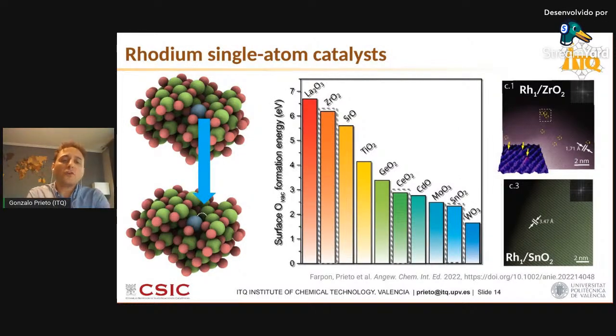At the beginning of this project, we set out to investigate one of these degrees of design for single atom catalysts, which was in particular our capacity to generate oxygen vacancies in the vicinity of our single metal atoms. Because already in other technologies, such as sensing, for instance, for light olefins, sensors rely on this interaction between olefins and oxygen vacancies, those type of surface defects. And that was the rationale we had at the beginning of this project.